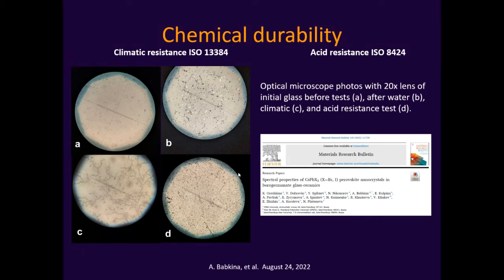And I made such tests of chemical durability, and I can say that these glasses are stable enough for massive production. So it means that we can take very unstable nanocrystals that are destroyed in several weeks, put them inside of the glass matrix and make them very stable. This material will have a life longer than we all will have. So after our death, they still will exist and will be luminescent. Most of these results are published in this paper.